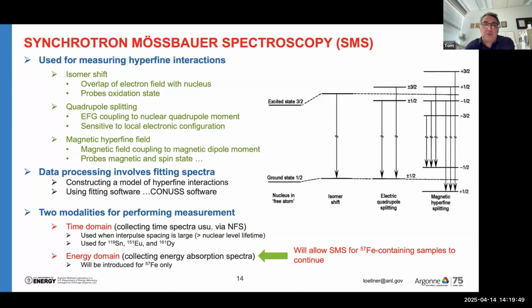Quadrupole splitting, you measure the presence of an electric field gradient, which is very sensitive to the electronic bonding and just the general electronic configuration. And because the nucleus has a magnetic moment, you can probe the coupling to the local field. So you can tap into the magnetic ordering or the spin state of the sample.